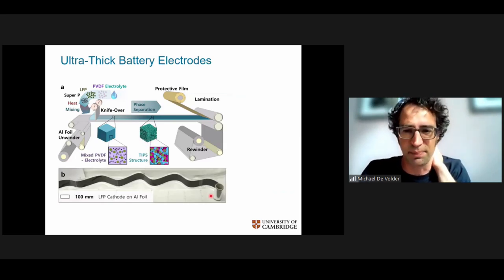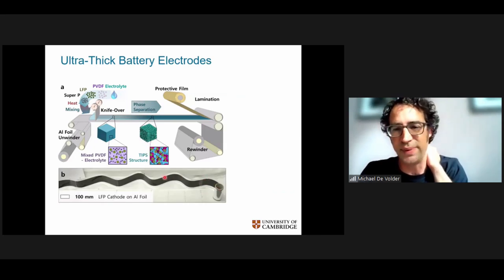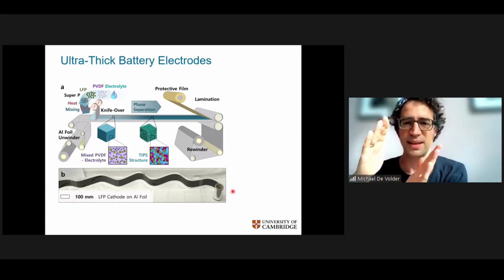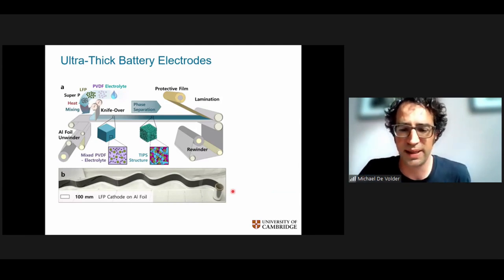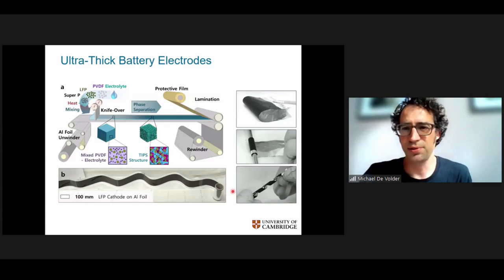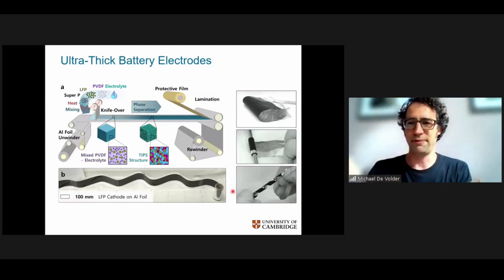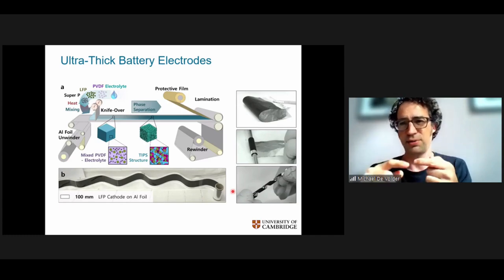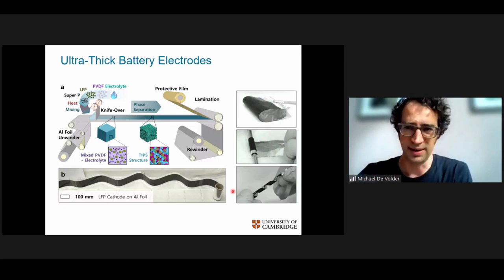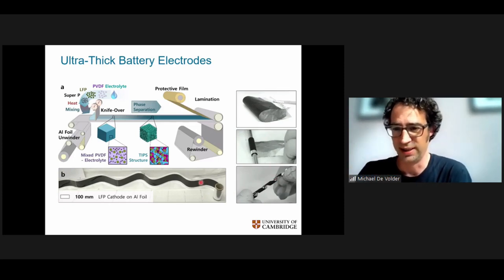And here you can see an example of several meters of coating on an aluminum foil in this case for these batteries. The coating was about 10 centimeters wide and several meters long. And so what we also tested then is whether these foils can be twisted and turned, because oftentimes when you take a battery electrode, you have to wind it up in a cylindrical cell, and it's important to check that the coating would not delaminate, and that didn't happen, as you can see here.